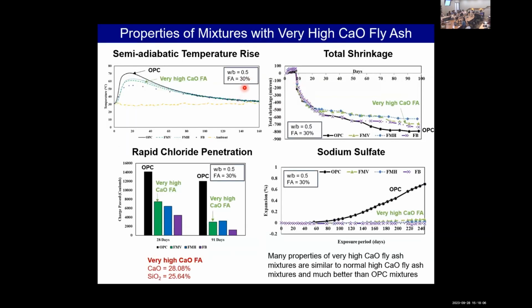And what about other properties? We also tested other properties, and we can see that many properties of the very high calcium oxide fly ash mixture are similar to the normal high calcium oxide fly ash mixture, and much better than cement or OPC only, like temperature rise, rapid chloride penetration, total shrinkage, and even sodium sulfate resistance.